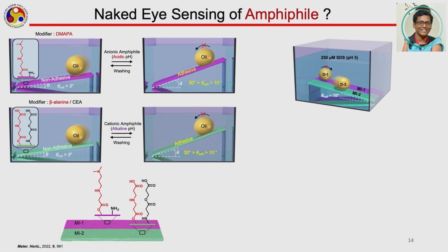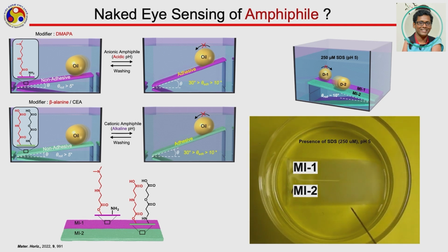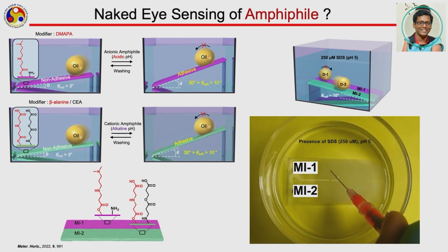Now see these particular demonstrations where this patterned interface was placed in submerged conditions in an aqueous phase, with 250 micromolar SDS, a negatively charged surfactant, at pH 5. When you put the oil droplet on this modified interface 1 where I have the cationic group, you see the droplet is stuck, it's not rolling. Obviously the surface is tilted at a 10-degree angle, whereas for modification 2 you put the same size of liquid droplet and it's instantly rolling.